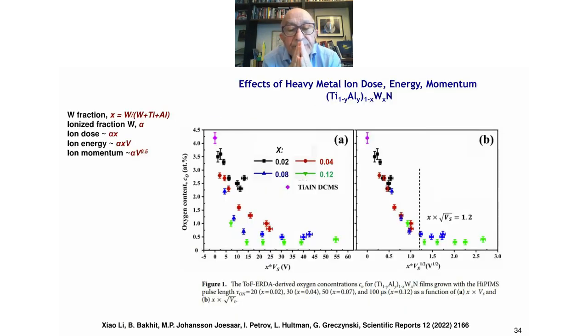Next slide. Here we try to compare the momentum and the energy. The same data for the oxygen content or the density in the film is plotted as a function of deposited energy. It is much more scattered than when we plot it as a function of deposited momentum. And there is a critical value of square root of v of 1.2, where we can choose dense films. And by looking at the previous map, we can choose dense films with relatively low stresses.